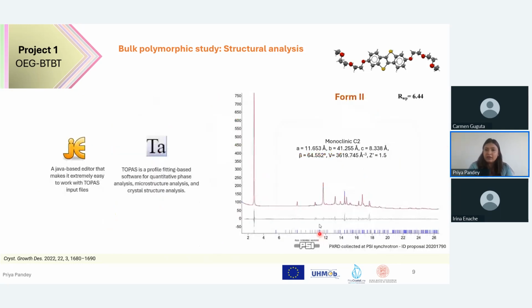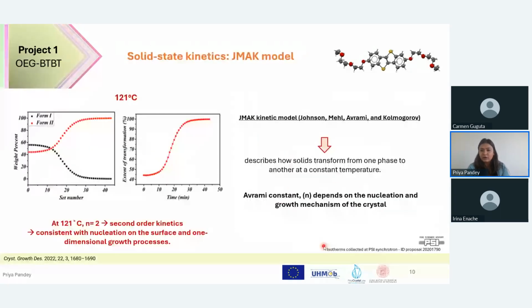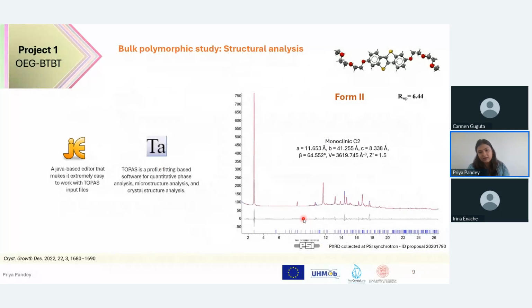Then there was form 2 that exists at high temperature. The problem with high temperature polymorphs is that they get highly disordered, or there are more degrees of freedom at high temperature, due to which we cannot collect the crystal structure using single crystal XRD. But I had access to the synchrotron, and I collected some high quality powder diffraction data.